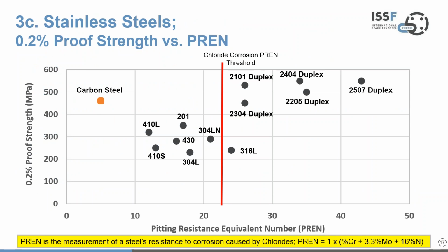So in this chart, we are looking at the 0.2% proof strength of mainly stainless steels, but carbon steels included for completeness, against what is known as the pitting resistance equivalent number, which is a measure of corrosion resistance primarily caused by chlorides. And I've put a red line on there that is a chloride corrosion threshold or indication of where you get poorer corrosion to the left and excellent corrosion resistance to the right. And what you see here in this chart is carbon steel has an excellent proof strength value, just shy of 500 megapascals, but that's very comparable with the duplex family of stainless steels to the right. And you can see as you move into the higher duplex stainless steels, the resistance to corrosion improves dramatically. So here, thinking about the duplex family, you've got the combination of really high strength and excellent corrosion resistance.